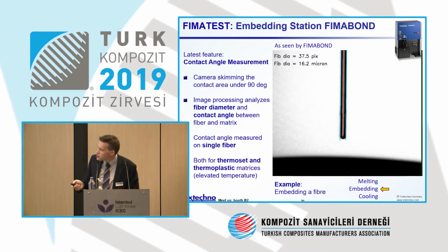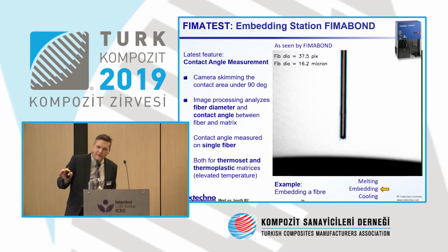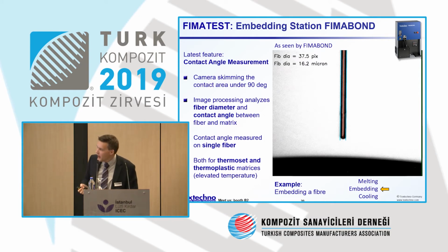There's one thing I'd like to show you inside the FIMA bond. It's the latest feature, and I don't have it here on the booth because the device isn't equipped with that. So I would like to show it here in the video: while embedding this fiber into the droplet, we are now also able to measure the contact angle between the matrix and the fiber at high temperatures, up to 400 degrees. And this is, of course, giving an additional measure of the bonding quality, because now you learn about the contact angle, telling you about the wetting quality of your matrix system. So that's actually the latest feature that we've just presented this year at the JEC for the first time.